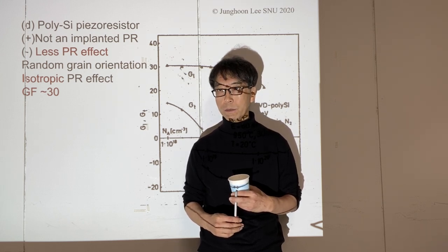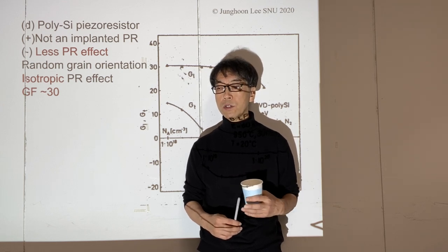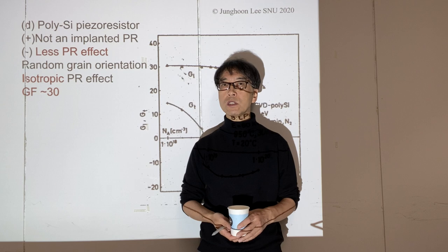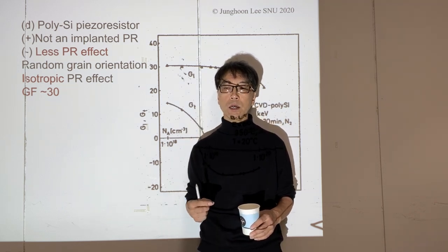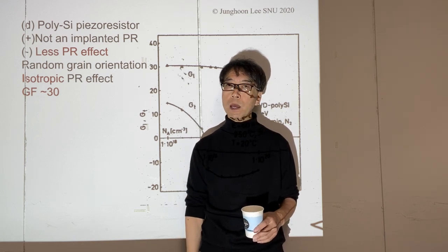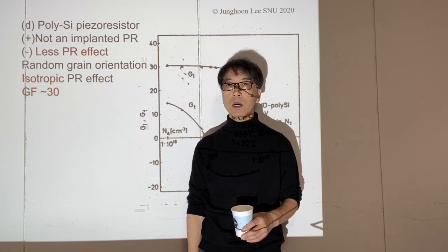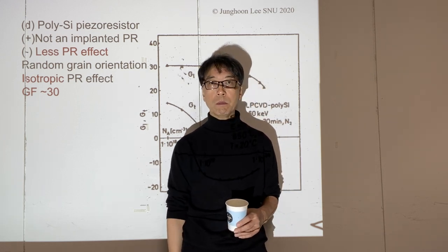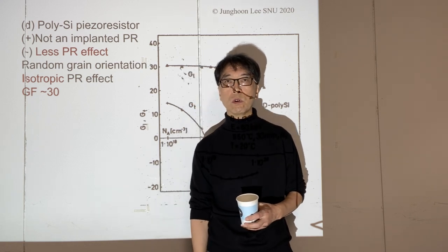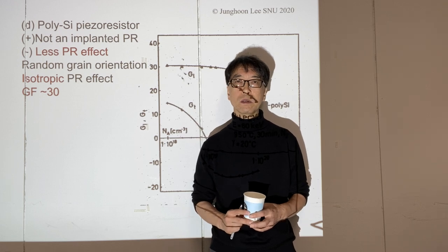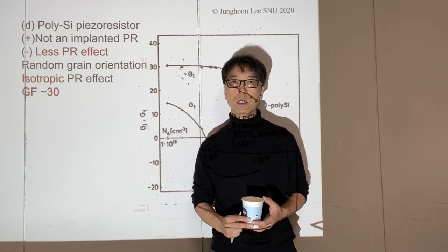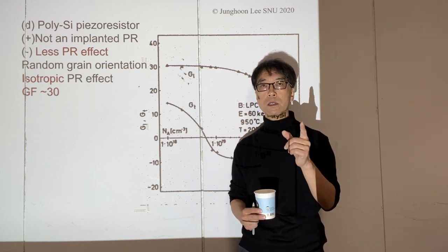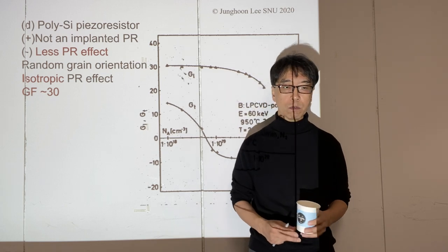And you have a freedom of using polysilicon, unlike single crystal silicon, where you need to have the whole body made of single crystal, which is pretty difficult. You know how difficult it is to create the membrane, the cantilever structures made of single crystal silicon. However, if you create, for example, a thin silicon nitride membrane, that's going to be easy. Nitride membrane will survive in the potassium hydroxide etching, leaving a very thin layer, submicron thin, something like 0.5 microns, 0.2 microns. And on top of that, you can pattern polysilicon, and you can use polysilicon as piezoresistance with gauge factor of 30. Wouldn't that be nice?